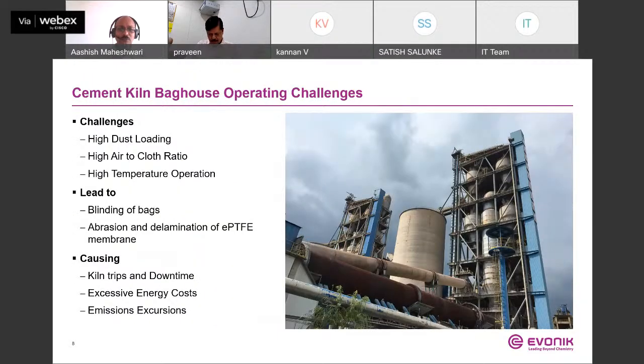Now, the kiln is one of the hearts of the cement application. What challenges did we find? Once there is high dust loading, high air to cloth ratio, there may be high temperature operation, and that results in the blinding of the bags. Or there are mechanical failures, abrasion and delamination of the PTFE membranes. Ultimately, this will result in excessive energy cost. At the same time, emission goes up and there is a production loss because of the kiln trip and downtime.